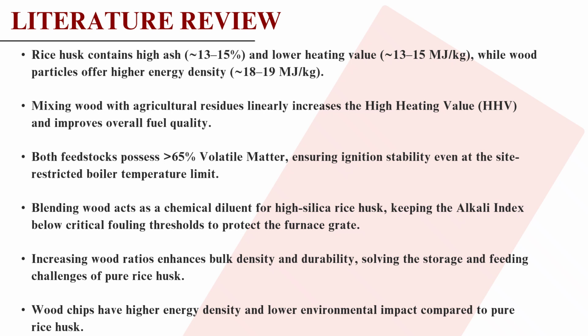In my literature review, I analyzed the core scientific reasons about the renewable energy feedstock. Rice husk has high ash content and low energy, while wood chips offer much higher energy density. Past research proves that mixing these two linearly increases the high heating value and improves the overall quality of the fuel.